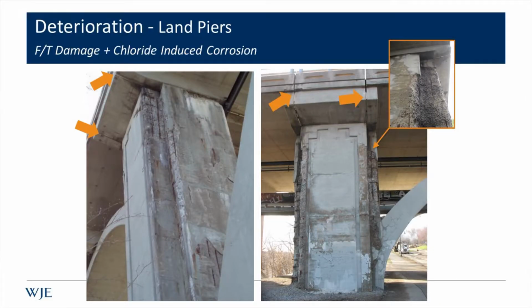There were 2 piers on each edge of the river, and out of the 15 expansion joints in the deck, there were 2 on each side of each of the land piers. And as you may know, expansion joints leak over time, and this was a 1923 bridge. So leakage over a long period of time resulted in both chloride-induced corrosion and also freeze-thaw damage, which the call-out photo in the upper right shows, an area of freeze-thaw damage below a leaking joint. And the damage on those land piers was pretty advanced.